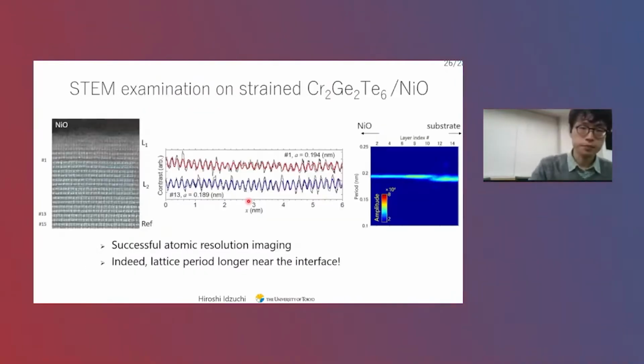Right. So finally, we examined this by using the scanning TEM method, on this strained CGT nickel oxide. So let me remind you, if we have CGT and form nickel oxide by sputtering, then we have some strain and some wrinkle structure. But without seeing this kind of structure, it's kind of indirect information. But if we really see this atomic